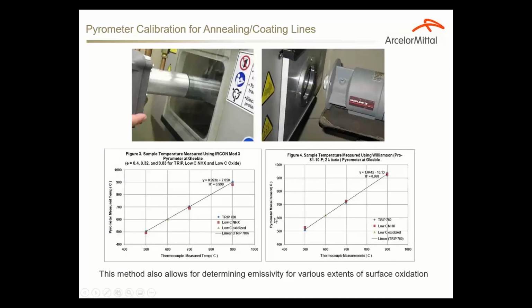One more application which we are very fond of is using the pyrometers. Pyrometers are being used all over the place, but mostly our concern is with the annealing and coating line. We measure the temperature of the samples in the Gleeble by thermocouple and by pyrometer. And when those temperatures do not match each other, that allows us to calibrate the pyrometer and to measure the emissivity of the strip.